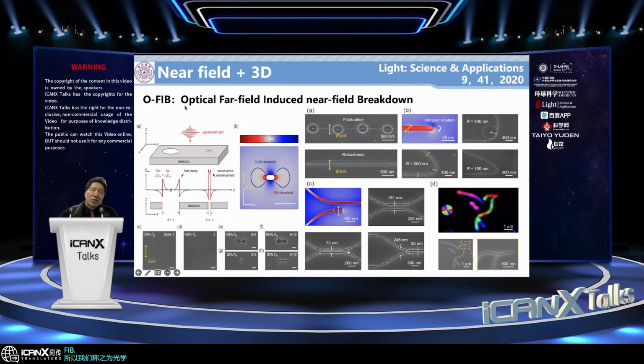You know, FIB originally means focused ion beam. We use a very similar name because we have very similar capability. But in our case, we don't use a very high vacuum to generate the ion beam. For the fabrication and resolution, our level is very comparable with the real FIB. In FIB, they can have nanometer level resolution, and we are a little bit worse, but already comparable. So this is what OFIB is.